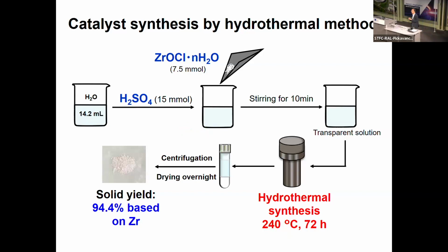You can obtain the white solid at the bottom. You can clearly obtain these materials. After repeating the centrifugation to get the solid, the yield is over 90%, which is very good. We don't have a loss of zirconia.